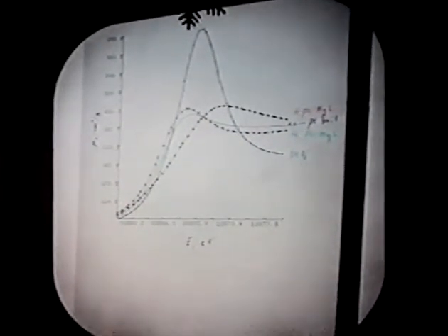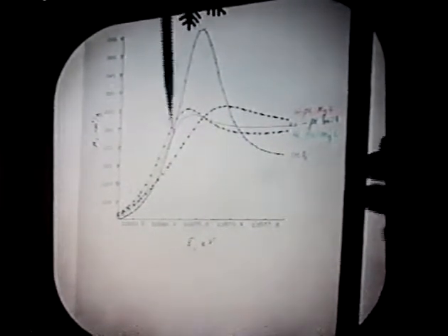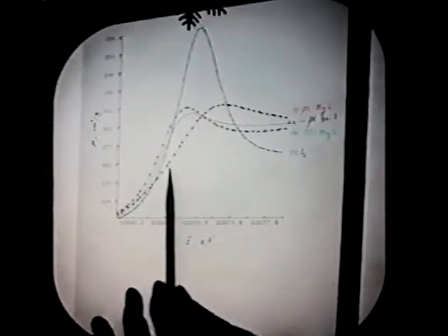Well, I made a lot of empty states at the Fermi level, and I got a big increase in intensity. So that is a qualitative measure of the density of states at the Fermi level. It's an electronic measure. Another bit of information we can get is the movement of this inflection point of the threshold, because that is a measure of the binding energy.